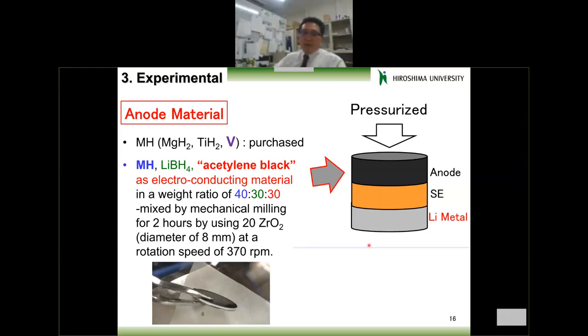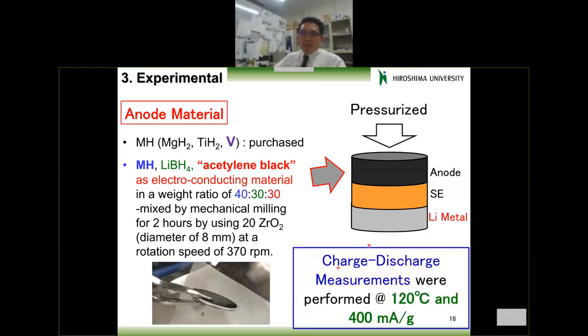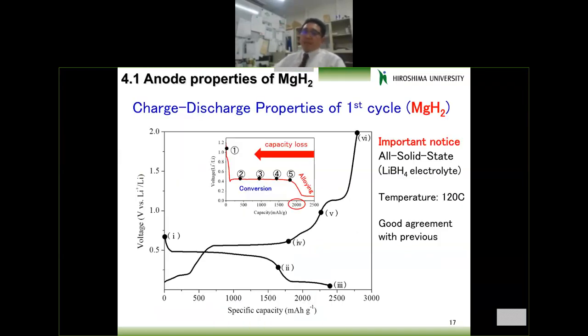And then finally, charge-discharge measurements were performed at 120 degrees C and 400 milliampere per gram. Because of the structural phase transformation, super ionic conductivity can be observed. So that's why we set 120 degrees C for measurement. Okay, this is the result.